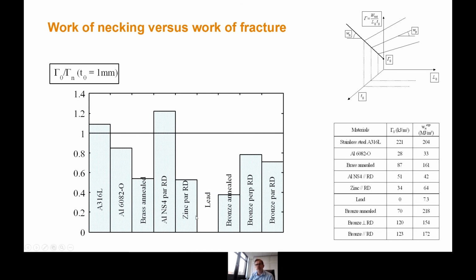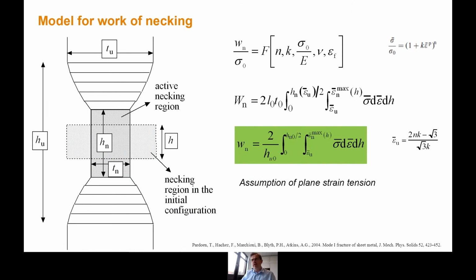And what you find for different materials is that sometimes the gamma 0 dominates. This is an example for this aluminum alloy. But for other materials, you see that the work of necking dominates. The more you increase the thickness, the more the work of necking will dominate, because the gamma 0 will remain the same, but the work of necking will increase proportional to thickness. So you can have different scenarios, and the values are given on the right. Okay, perhaps I will go fast here just to show you, and if you are interested, please go in the paper. Don't hesitate to contact me if you have questions.